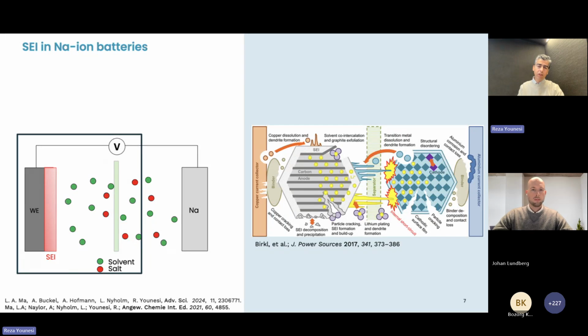Because if you look at the picture on the right, there are many different aging mechanisms in a real lithium-ion or sodium-ion battery. So it's very difficult to identify and quantify each one by one. What we try to do on the left is to mimic these different conditions in the cell and try to understand SEI formation and dissolution. As you see here, we form SEI on the working electrode, then we apply some relaxation or pause time, where there is no current or potential applied during this relaxation time.